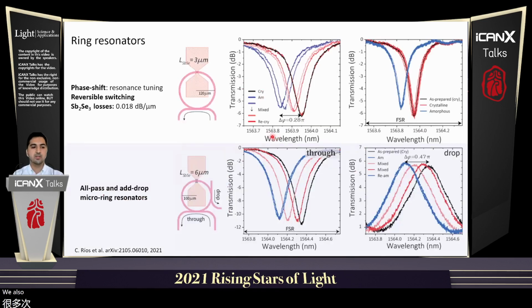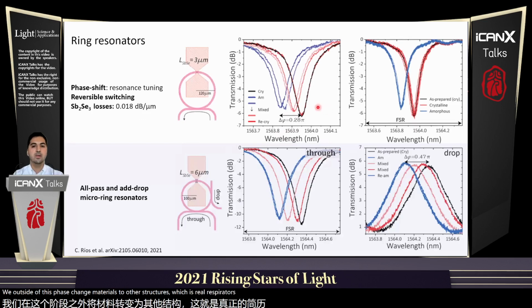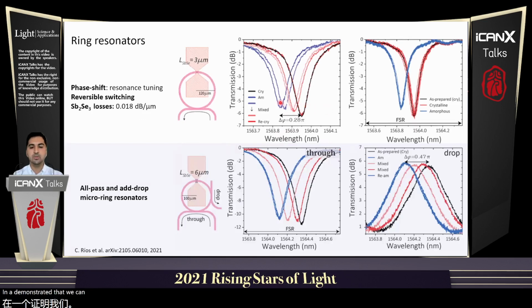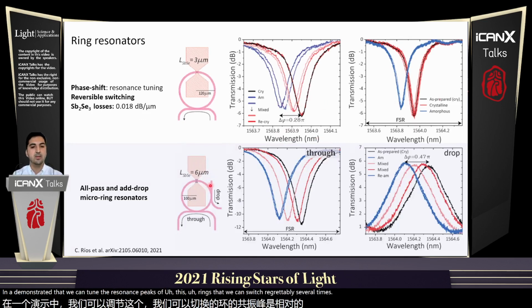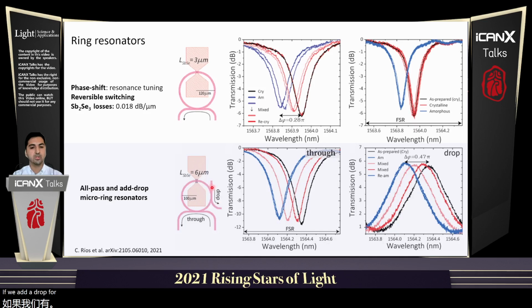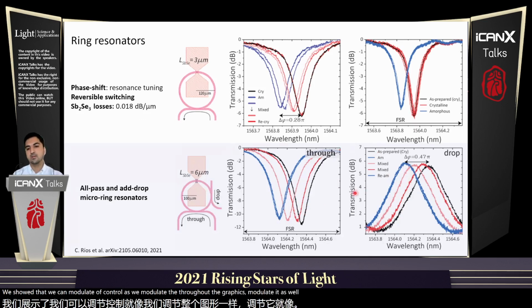We also added the phase change materials to other structures, such as ring resonators, and demonstrated that we can tune the resonance peaks of these rings, and that we can switch reversibly several times. If we add a drop port, for instance, here, we showed that we can modulate both. As we modulate the through port, the drop port is modulated as well. And this is very exciting.